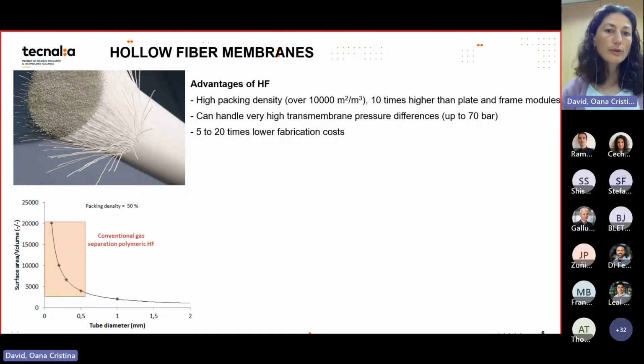And now coming to hollow fiber membrane. So here, as I said before, a hollow fiber is a tube with a diameter lower than 0.5 millimeters. They have a few advantages mostly in terms of packing density, because in this calculation, you can see here in the graph below left, we calculated the surface area divided by the volume that these fibers would occupy inside a tube, which is equivalent to a separation module.